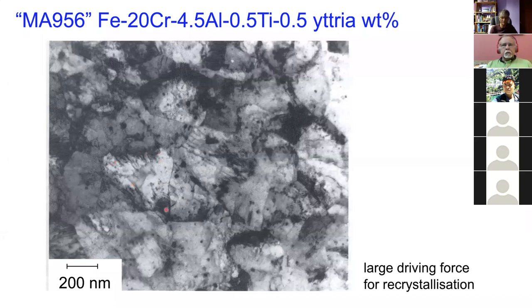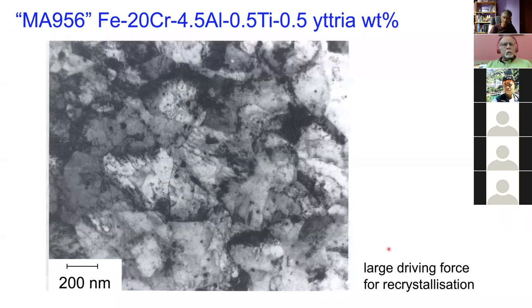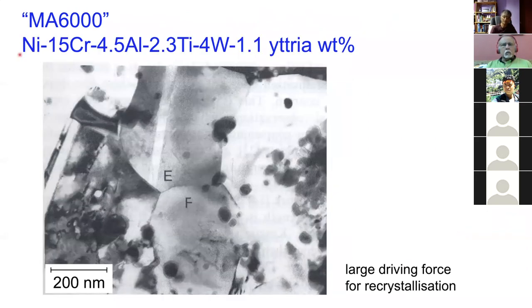There are extremely fine grains and a very large dislocation density, making the extruded material extremely hard even after hot extrusion. You can see myriads of small yttrium oxide particles dispersed throughout the microstructure, so there is a very large driving force for recrystallization. This is the commercial alloy MA956, which is ferritic. There is also a nickel-based version with chromium and aluminium for oxidation resistance, titanium, tungsten, and clearly visible yttria particles. Both have a fine structure with a large driving force for recrystallization.